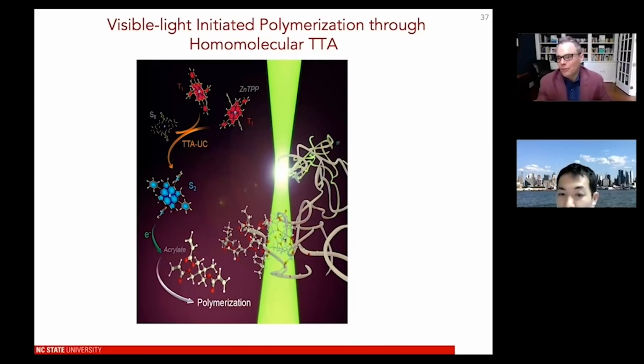When you're producing light and you're trying to produce stoichiometric reaction chemistry with photochemical upconversion, you need super high efficiency. The good news is for free radical polymerization, you need one electron to initiate it, then it goes. So you don't need it to be efficient. This is ideal for using an S2 excited state that has a lifetime of a couple of picoseconds to drive a reaction. And that's the beauty of free radical polymerization: because it's so inefficient, you can control the material really well as a result.